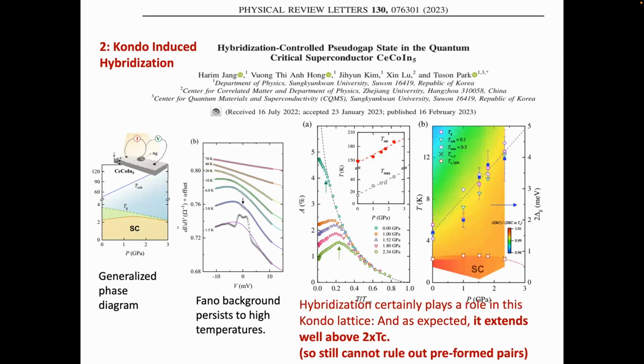Here's another example where Tuson Park and Xin Lu, my student who's now at Zhejiang University in Hangzhou, said, no, Green's group is wrong. It's not wrong, it's hybridization. The Kondo lattice shows hybridization between the f level and the conduction electron band. And I look at their data and I say, yeah, you're right. That's absolutely correct. But they also see this effect going all the way up to T star. So our argument is that we're both right, and I'll put on some explanation coming up, and then I'll show a couple of plots, is that we're probably all right. There's certainly hybridization, but it looks like in this material there are some preformed pairs above TC, and could that be the pairing mechanism in this material?